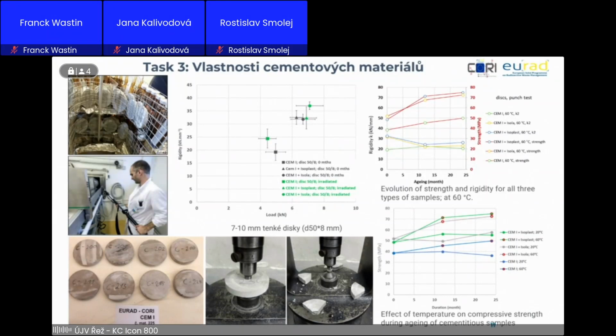Maybe some of you were yesterday at the speech of Patricia Halodová, so it was more or less the same: in some cases radiation can help the concrete, in some cases it can damage it. There are also some samples with plasticizer, but also in this case, either irradiation didn't cause any change, or it made some improvement. In case of simple aging, on the right-hand side, the older the sample, the better the properties, rigidity or strength. Strength was tested on the cubes and rigidity on the small slabs.